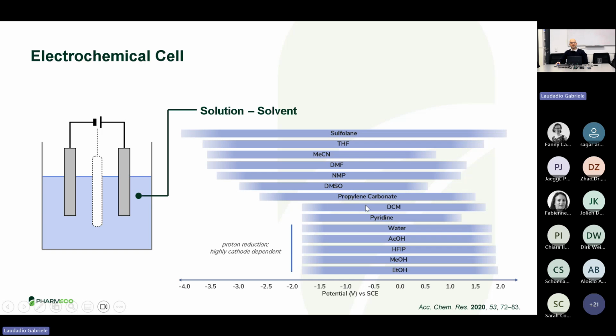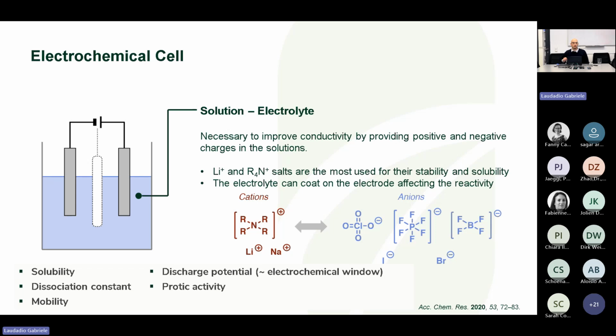Okay, so what happens if we have a solvent that we would really like to use, a solvent that has a very low dielectric constant? In that case, to increase the ions present in the system and also lower the resistance of the cell, we can use salts. We can add salts to our solution to maximize conductivity. In organic chemistry, the salts commonly used are tetraalkylammonium salts, because they are bulky and relatively lipophilic, so they can be easily solubilized in organic solvents, but also lithium and in some cases sodium can be used as cations. For anions, we usually try to use non-nucleophilic anions, so bulky systems like hexafluorophosphate or tetrafluoroborate. Perchlorates can also be used, but not on scale because they are explosive.